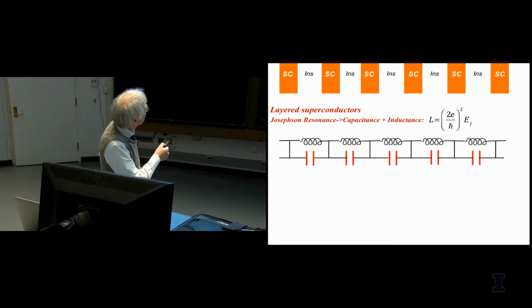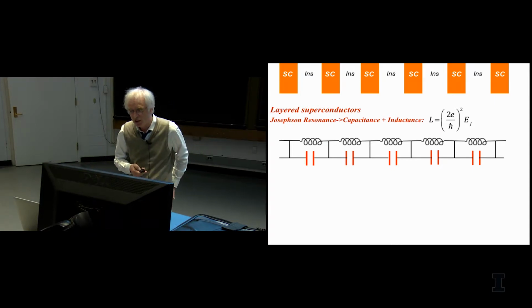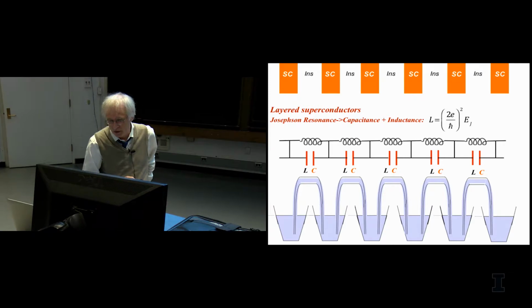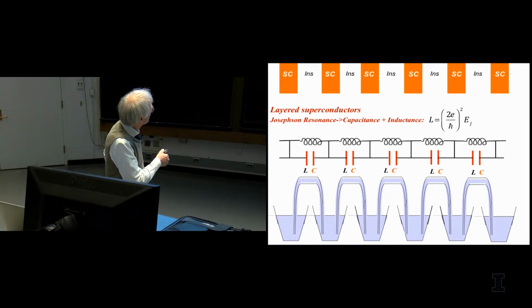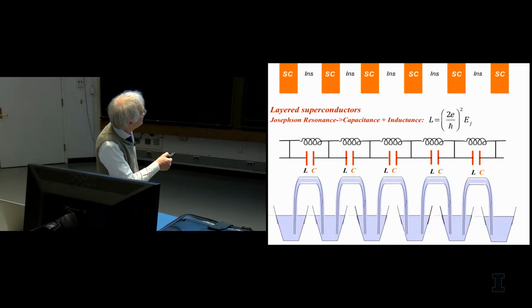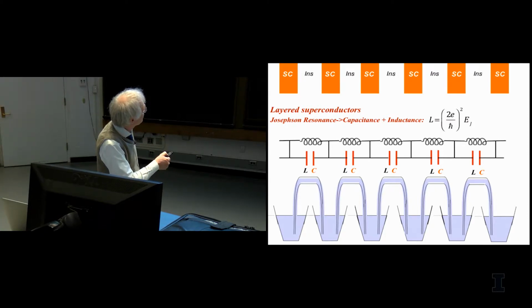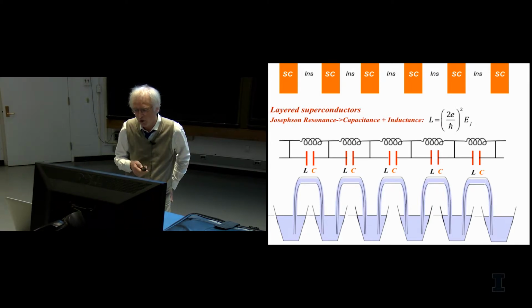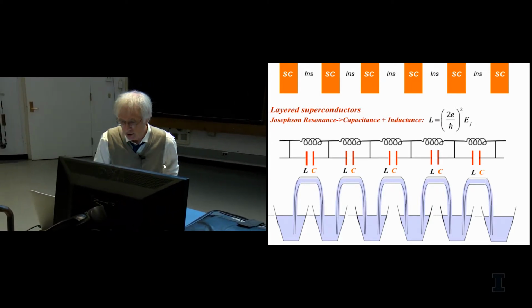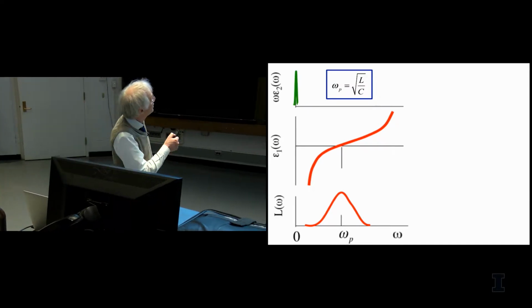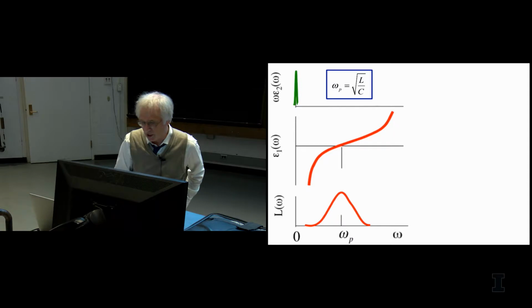So there's a sort of inductance given by the Josephson coupling energy times a universal constant, and the capacitance, which is essentially given by the geometry of your material. You can also think of each layer as a bucket filled with electrons, actually Cooper pairs, and they can flow from one bucket to the next. If you set up a plasma resonance from here to there, the total charge in each of the buckets remains the same, except for the extremal one. So the total charge oscillates between this one and that one, and actually flows through the other ones. That sets up a more or less ordinary plasmon, but made out of Cooper pairs. And the resonance frequency of that is given by the square root of the inductance divided by the capacitance.